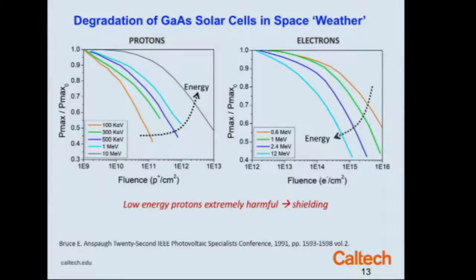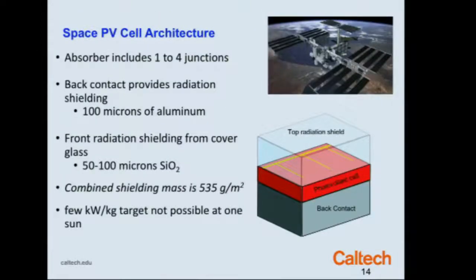Here's the problem. With something like a gallium arsenide solar cell, if we start at the beginning of life with some output efficiency, depending on the flux of protons between 100 kiloelectronvolts and 10 megaelectronvolts, I could lose more than half of the power generation over the lifetime of the mission, and this is a real problem. And likewise, with high-energy electrons that are part of the solar wind as well, which are of the order of a megaelectronvolt, there's a whole energy distribution from a little less than a megaelectronvolt to a few megaelectronvolts, we can also lose half the power. So these materials are very radiation sensitive, and we need to put shielding on top of our solar cells.